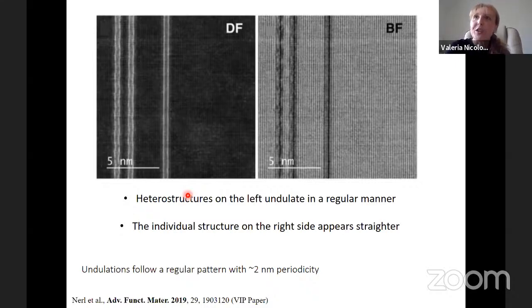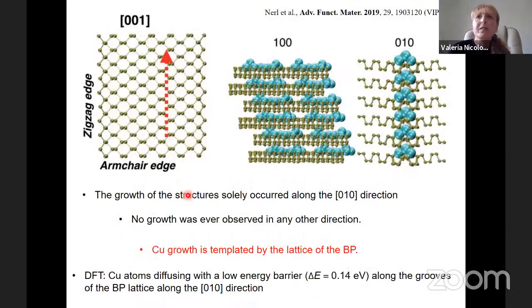It was quite intriguing, so we did a lot of simulations. We did a lot of DFT calculations to understand what was happening. And we understood that this copper always grew along the 0-1-0 direction, and it was never observed to happen in any other direction. And it really followed the template structure of the black phosphorus. It always went on these interstitial positions here.